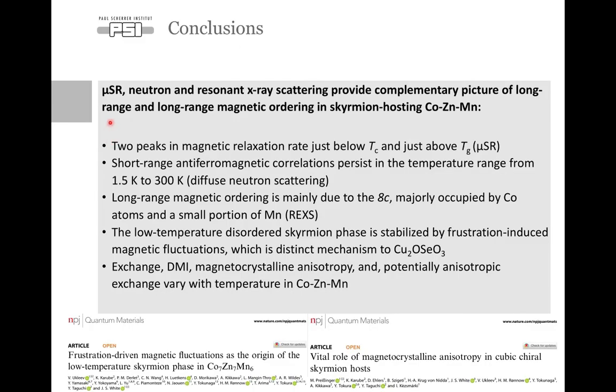Just to conclude, we used multiple quantum beam probes, namely muons, neutrons, and soft X-rays, to provide a complementary picture of the long-range magnetic ordering and short-range correlations in Skyrmion hosting cobalt zinc manganese alloys. We have observed two peaks in slow magnetic relaxation rates just below TC and just above the spin glass transition in this material. And we connect the low temperature peak with the stability of the low temperature disordered Skyrmion phase. Also, we have successfully observed short-range antiferromagnetic correlations that persist from lowest temperatures to 300K in cobalt zinc manganese alloys.